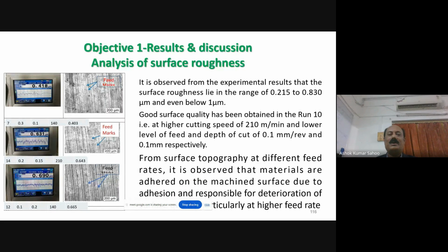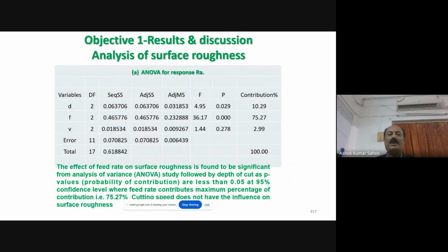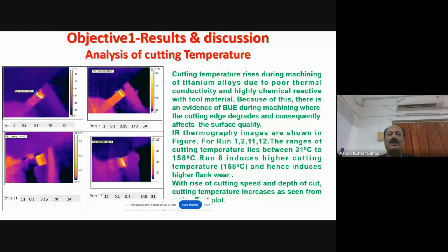Surface quality is obtained, and feed marks are clearly observed on the surfaces through the metallurgical microscope, and it is also measured through the Taylor-Hobson surface roughness tester, where it ranges between 0.215 to 0.83 micron average surface roughness, Ra, which is well within the 1.6 micron standard that we have taken as per ISO standard. And feed is found to be the significant parameter for surface quality in ANOVA analysis.